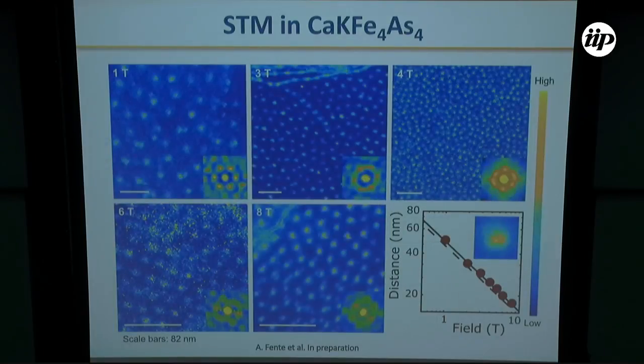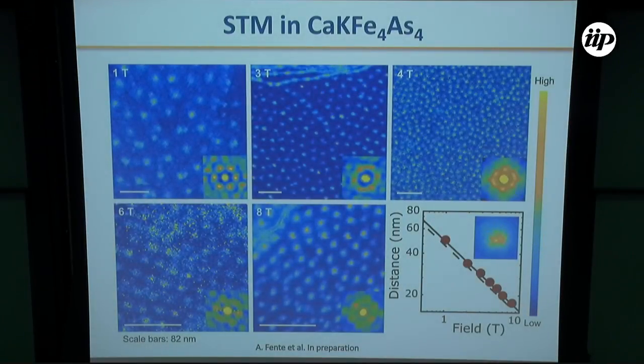When we apply a magnetic field, we have seen the vortex lattice as a function of the magnetic field from 1 Tesla up to 8 Tesla. The vortex lattice has hexagonal symmetry, as can be seen from the autocorrelation function images.